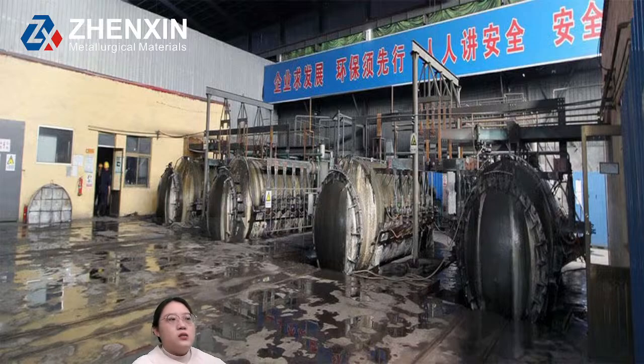When buyers choose ferrochrome nitride, they usually face three key challenges. Just check if you also face these challenges. The first challenge is composition stability, because unstable nitrogen or chrome means unstable steel quality. The second challenge is delivery. Long production cycles or delayed shipments cause furnace downtime. The third challenge is compliance and payment, because some suppliers can't provide proper ISO or third-party documents.